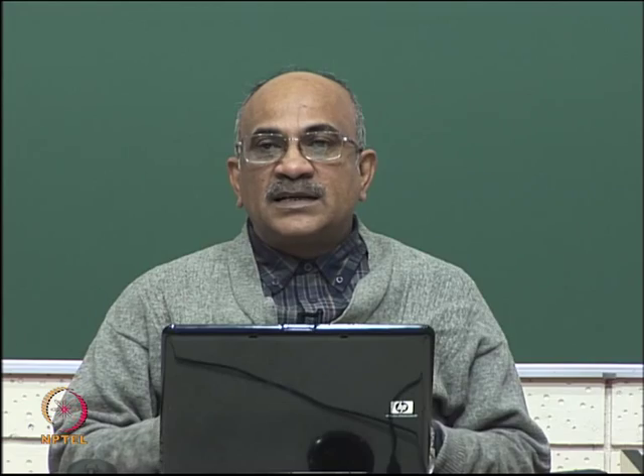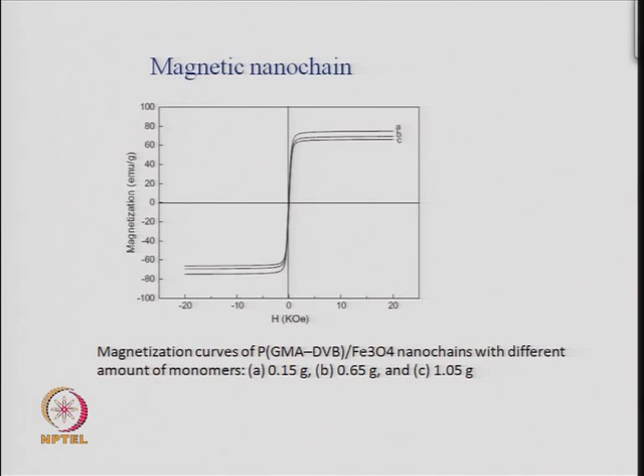In both of them, you can do magnetization as a function of field, and when you do that study on these magnetic nano chains, you see this super paramagnetic behavior. This is what I described earlier, that any super paramagnet will show a behavior where it will go through the origin. That means, the remanent field should be 0 and the coercive field will be 0. So, all the three compositions made with three different amounts of monomers show the same super paramagnetic behavior, which we explained earlier.